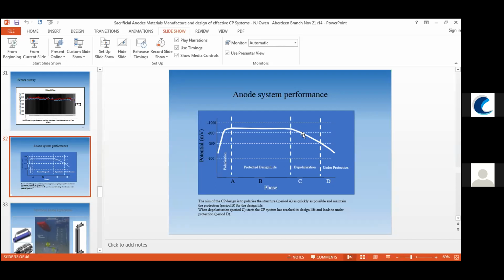This is due to the reduction in the size of the anodes and the output of the anodes as a result of that. You start to get a falling system, and the protection levels for steelwork are generally from -800 versus silver chloride electrode. And where you've got severe accelerated low water corrosion, as we do in harbours and things like that, they do specify you can use a level of about 900. And that just shows you this is the time in the depolarization and under protection.